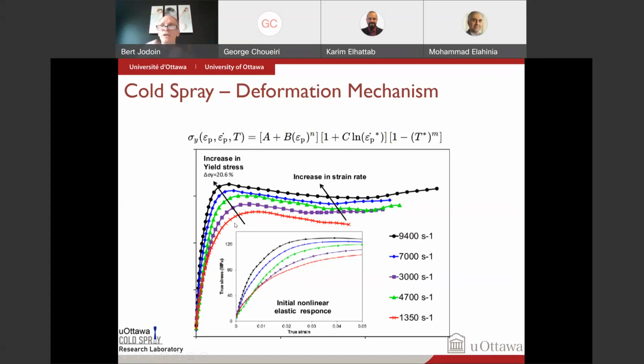And if you want to have the same material and deform it quicker at a higher strain rate, you're going to need to pull harder because of some irreversibilities. So it's harder to deform at the same strain at a high strain rate. If you want to bend something slowly, it's easy. If you want to bend it fast, you need to work a bit harder. If you remember from your materials courses, the area under this curve is the work. Most of this work is lost as heat transfer. A little part of it, about 10%, is really going into modifying the microstructure, getting dislocation movement and all that to get your deformation. So when you have a high strain rate like that, you're producing even more heat, right?